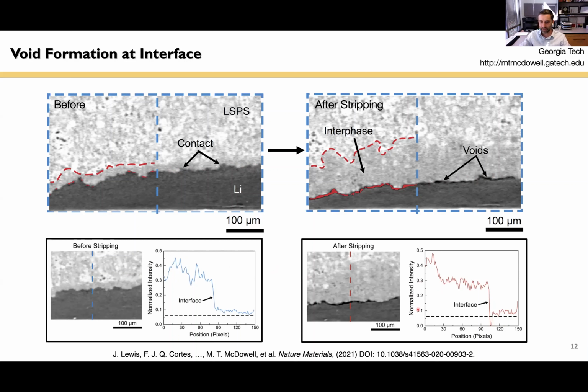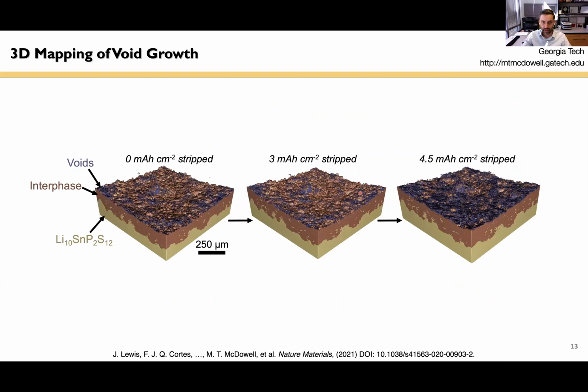So you can see the normalized intensity at the void spot. It's our lowest intensity. And so we're able to segment and separate the lithium intensity from the void intensity, from the solid electrolyte intensity. And that allows us to map across three-dimensional space the presence of all these different phases as a function of time. And the result is a lot of data, as you can imagine. Some of that data is shown here.